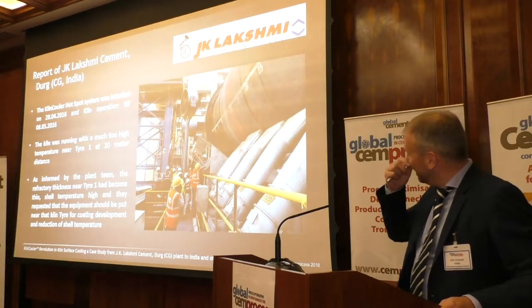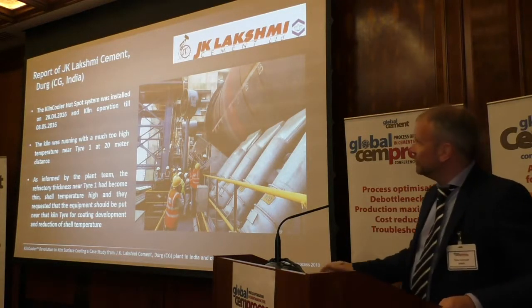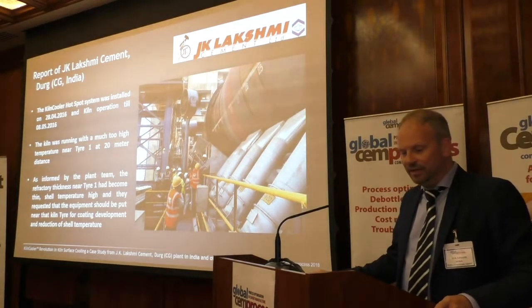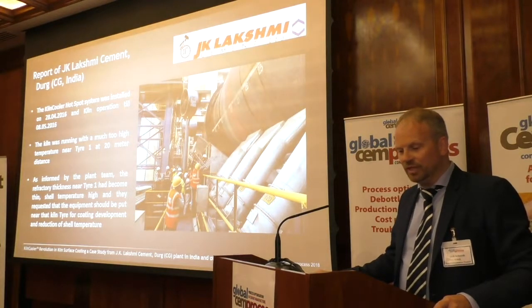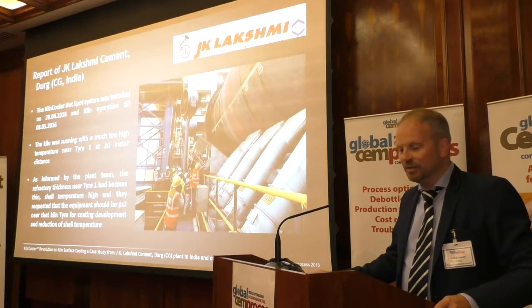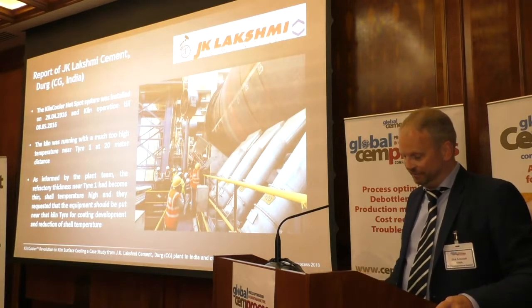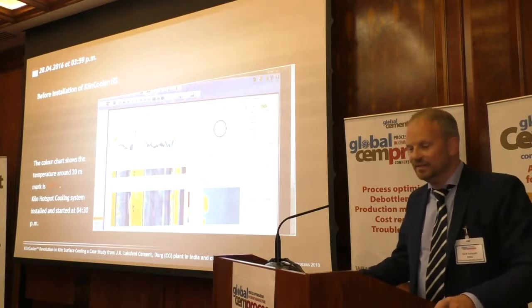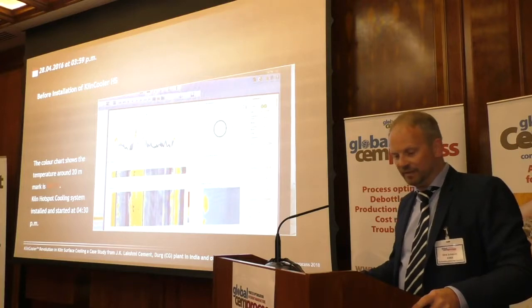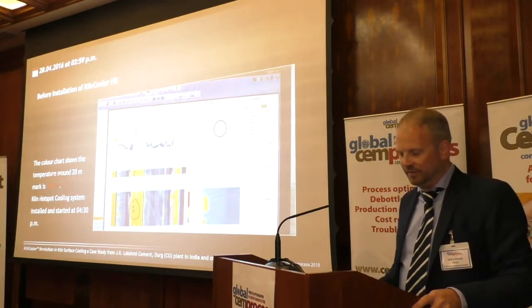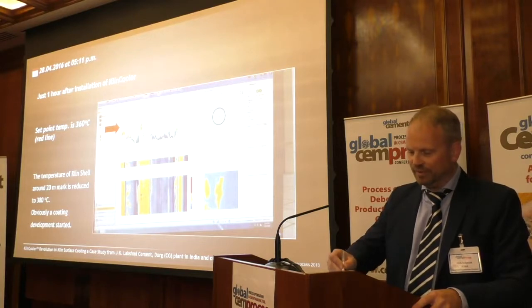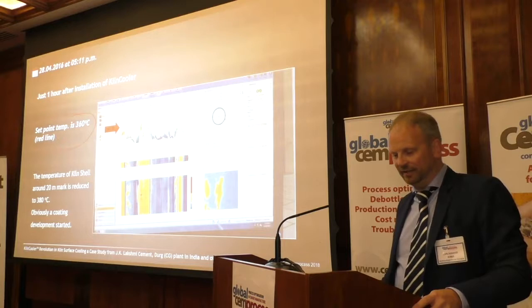I give you an example now, as also reported in the catalog, from JK Lakshmi Cement, which was done already in 2016, when the kiln was running at a much higher temperature near tire 1 at 20 meter distance because of very thin refractory. The plant team said that it had become very thin and they had to do something. However, we installed the system, and now let's see the temperature screen before we started the system. We have here a temperature of 397 degrees as peak. You see here on the thermoscan also these peaks. Just 1 hour after installation, we adjusted a set point, as you will see in the next slide, at 360 degrees, only to prevent this overheating. Nothing else.